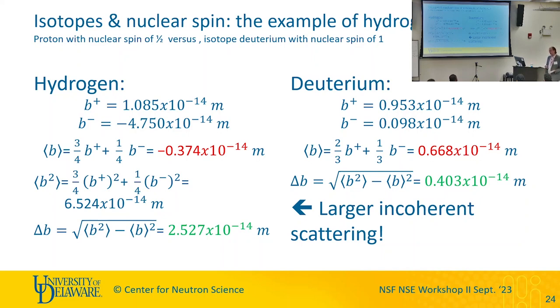If I want to look at dynamics, we'll see some quasi-elastic neutron scattering, where I might want to look at the hydrogen moving, because it has such a large incoherent cross-section, and that's what we measure in that technique. And in other techniques, we measure the coherent scattering. We don't want that noise. So we work in D2O not only to get contrast, but also to reduce the background.